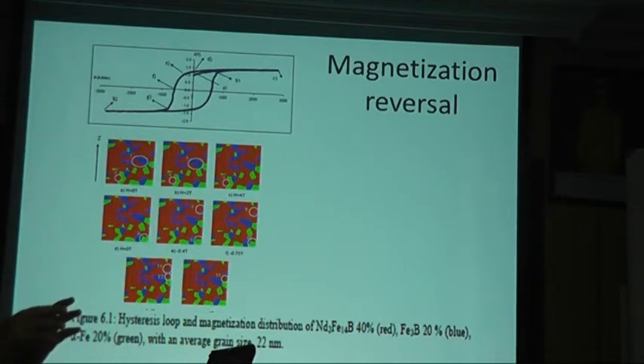But in experiment, we cannot arrange the position of soft and hard. But in simulation, we can do the arrangement. In my case, we do it in random because we want to make it real. So when we apply a magnetic field, we can see from here the difference of magnetization arrangement from 2 Tesla, 4 Tesla, and then we make a reverse field. So we can study what happened to the magnetization. We cannot do that in the real magnet.